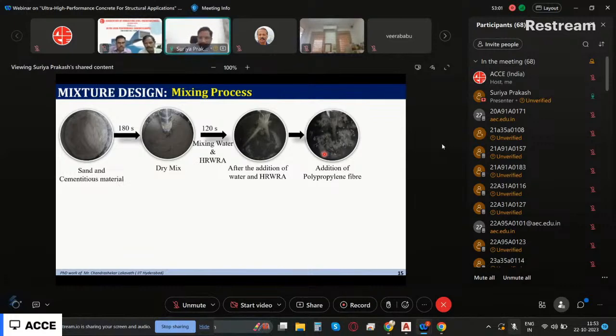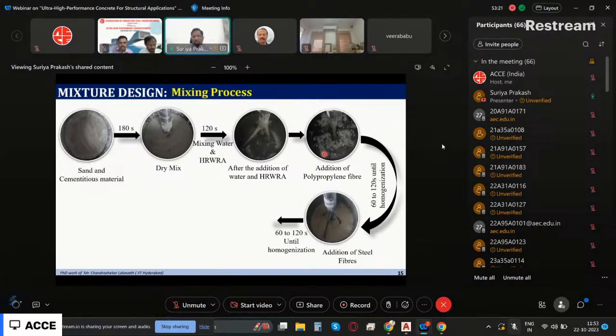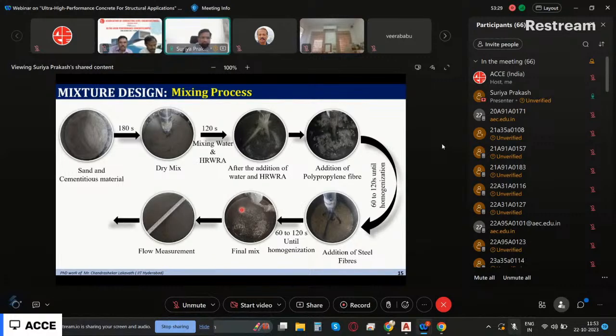These are microfibers just for arresting the shrinkage, because in UHPC we use a very high amount of cement content, in the range of 800 kg per cubic meter. When you use such a cementitious content, shrinkage cracking can be an issue. So we add a very small dosage of polypropylene fiber. Then again we mix for 60 to 120 seconds, and then we finally add the steel fibers. Then again we mix it for about 2 minutes. Then you finally get this kind of a mix, and then we check for the flow.